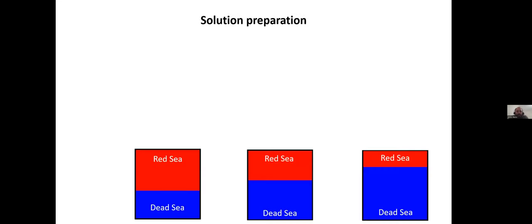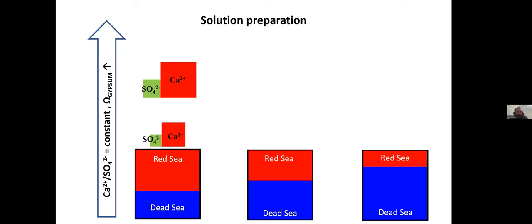Now, each mixture I make between seawater and Dead Sea brine would have its own oversaturation and its own calcium to sulfate ratio. And I wanted to know how each one of these parameters impacts the morphology and the kinetics. So what I did was make different mixtures between Red Sea and Dead Sea brines. Each one of them has its own composition, and to each one I added calcium and sulfate in different amounts but in the same ratio as already in the initial brine. In this way, I could have a constant calcium to sulfate ratio but different oversaturations.